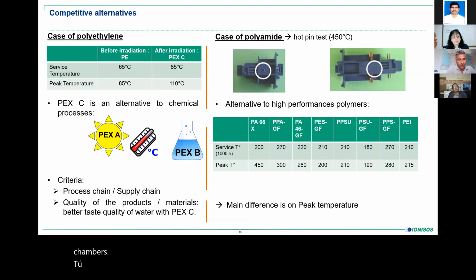Here we have another two examples, more related with the treatment of pipes for underfloor heating. This is, let's say, one of the most common applications at the moment. These pipes made of polyethylene, after the treatment, can withstand a service temperature of 85 degrees, while normally they can only go up to 65 degrees. And also for the peak temperature, we are able to use these pipes for heat applications, while normally this polyethylene would not withstand the high temperatures of the water.